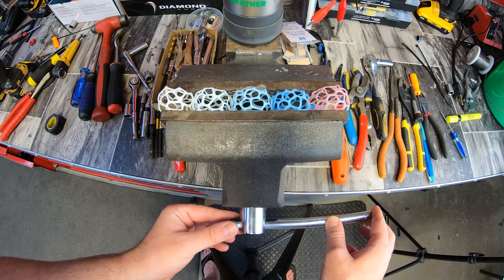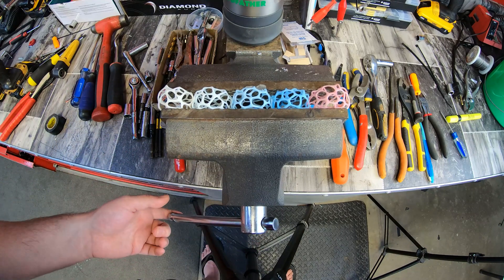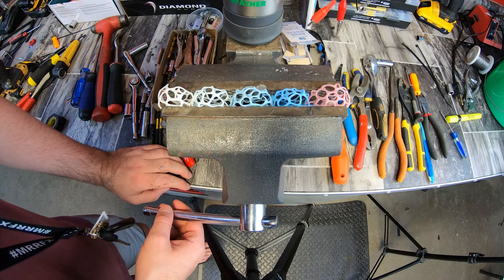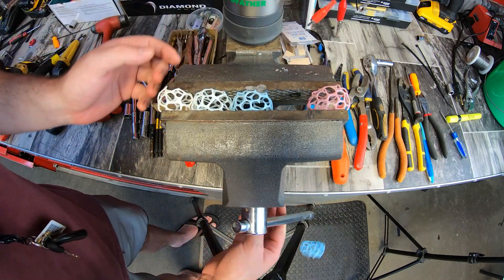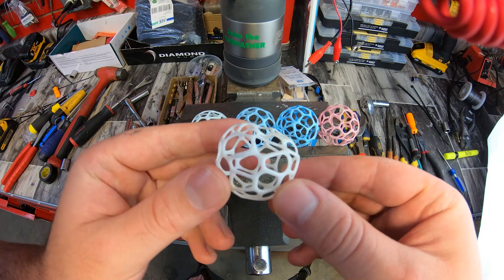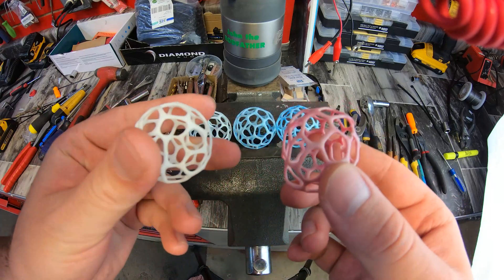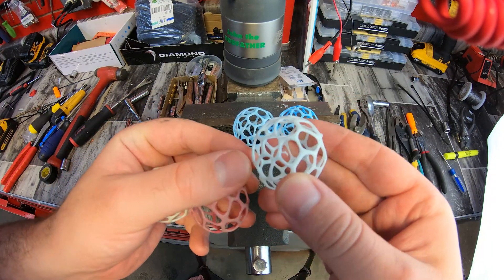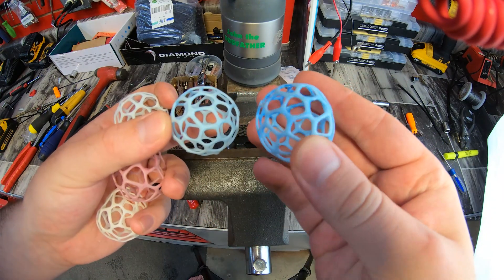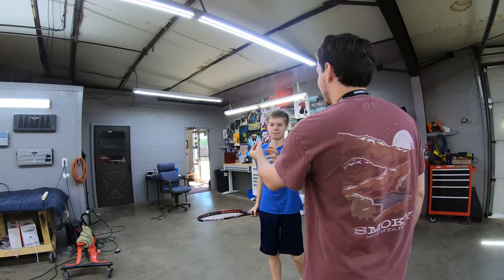This one cracked. Let's say one cracked. Third one cracked. All right, let's see if these two are still alive. So after about five minutes, the zero percent Tenacious was not able to regain its shape, and the Sunlu nylon type was not able to regain its shape either, which is interesting. The ten percent also had trouble regaining its shape, but the twenty percent and the thirty percent seem to have regained their shape even though they're broken in some areas — an interesting result.